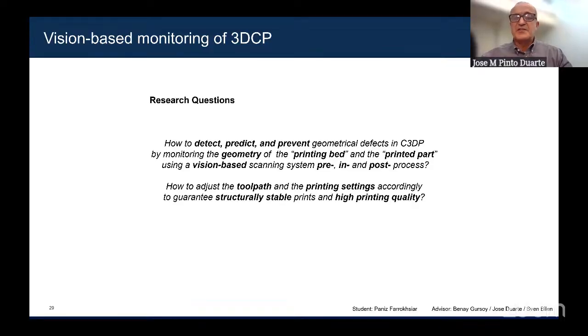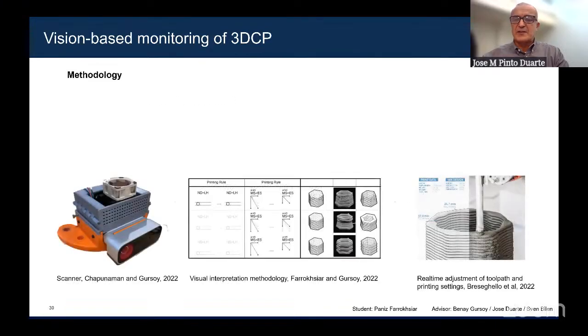This is the work of another PhD student to detect, predict, and prevent geometrical defects in concrete printing, and how to adjust the toolpaths and the printing settings in real time to prevent that from happening. So you can see some images of the machine and the process being used. We are basically using shape grammar rules to decode what the machine sees, what the camera sees, and define and trigger the right action, which might be, as I mentioned before, the content of water, or the speed of the pump, or the speed of the robotic arm, or even a change in the toolpath.